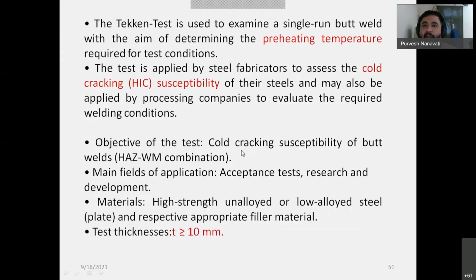There's a geometry, and the Tekken test is used to examine a single-run butt weld, determining the preheat temperature required for the test condition. Because when you have a preheat, the solidification time or cooling rate is controlled. So your hydrogen has an opportunity to escape out of the weld metal. As a result, there will not be traces of entered hydrogen, and you will be away from any possibility of hydrogen-induced cracking.